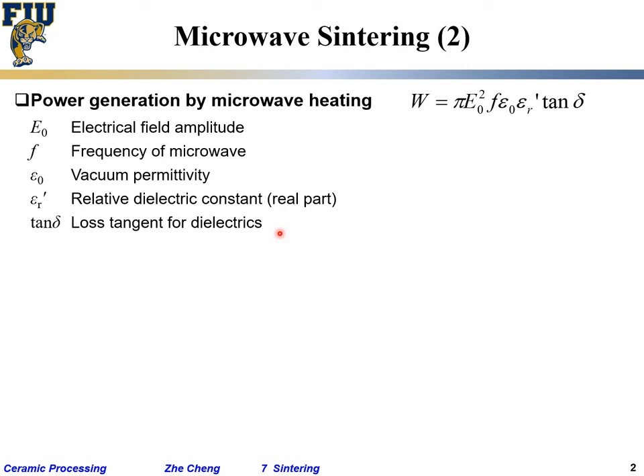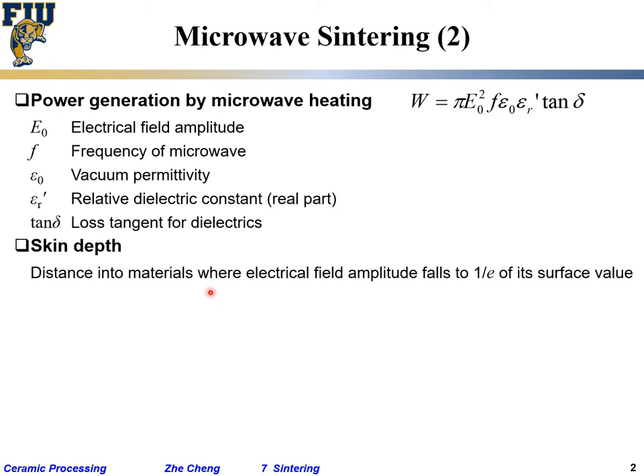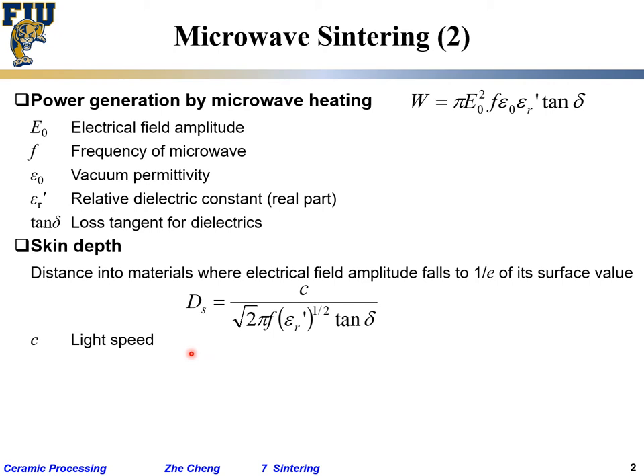Knowing these parameters tells us how much power or heat dissipation would happen within the material. For microwave, there is a parameter called skin depth — how deep into the material the electromagnetic vibration would reduce to 1/e of its surface value. Essentially, it describes how fast the material absorbs microwave within it. For microwave in metals, the skin depth is only about one micron, meaning the majority of the microwave energy drops within that very thin layer of metal.